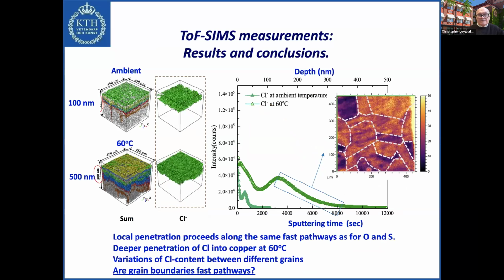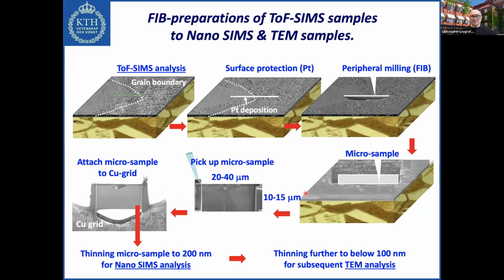Here's a third element, chlorine. And here again shows the same type of results. The ingress is not as pronounced as for the other two at 60 degrees, but definitely more than at room temperature, and a variation between different grains. So the question is now, are the grain boundaries these fast pathways, or is it something else? So for this, we now go to the next two types of techniques that we have been using.